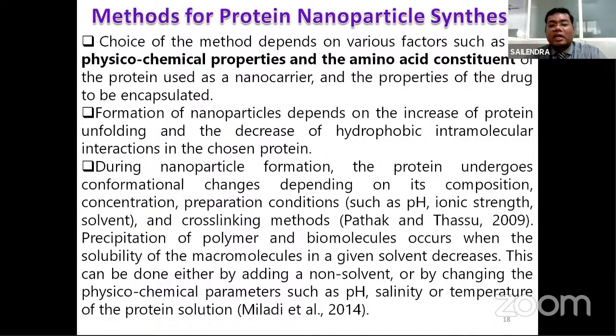Where you can modify the protein unfolding and refolding, and you can decrease the hydrophobic intramolecular interaction in the chosen protein, and you can get the desired particle size at the desired condition of the protein. During the nanoparticle formation, a lot of interactions keep on going on when the protein is changing its structure. Hydrophobic residues will come onto the surface, or if the hydrophobic residues are on the surface, they will keep on moving to the inner part of the nanoparticle.